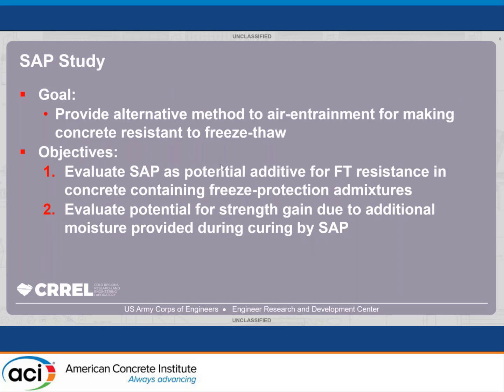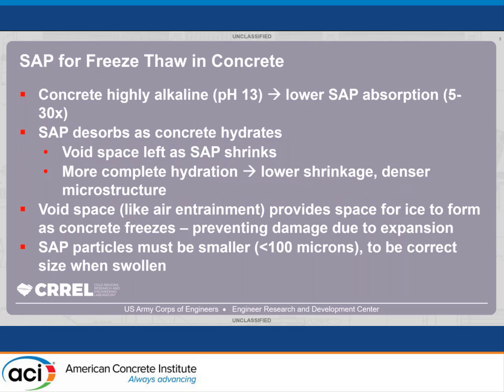A little bit more on SAP in concrete to be used for freeze-thaw. Concrete, as you guys know, is very highly alkaline, and that changes how much the SAP will absorb. So as I said, if this were in fresh water, it would be able to absorb over 100 times its own size. But in this very highly alkaline material, the SAP absorption is much lower. It's not fully understood, but somewhere between 5 to 30 times.